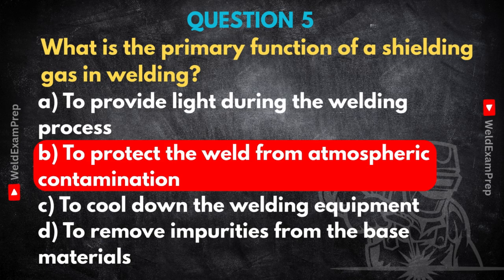Oxygen reacts to form oxides, which can get trapped to make the weld weak and brittle, causes porosity too. Nitrogen can make the steel brittle, cause porosity, even lead to cracking later on. Both really degrade the mechanical properties, the strength, the toughness of the weld, makes it unreliable. So the shielding gas, whether it's argon, CO2, its main job is to push the air away. It creates this protective bubble and envelope around the arc and the molten pool. It physically blocks the oxygen and nitrogen from getting into contact with that super hot reactive metal